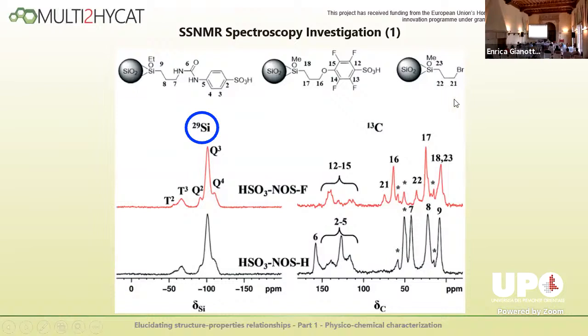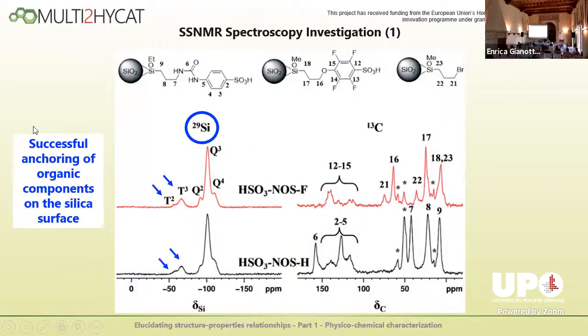As for the successful grafting, so the integrity of the hybrid material, with solid-state NMR we can monitor, for example, the successful anchoring of the organic components on the silica surface by monitoring the silicon NMR, because we see the T2 and T3 signals that are due to the grafting moieties that in the normal silica are not present, because only the Q signals from the bulk are visible. The integrity of the organic components is assessed by carbon NMR.